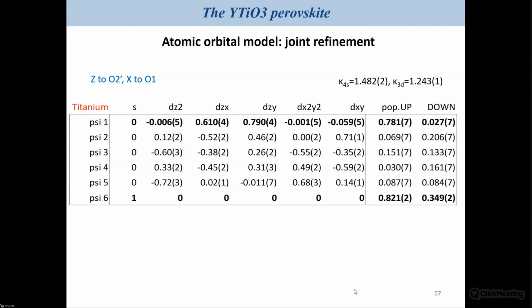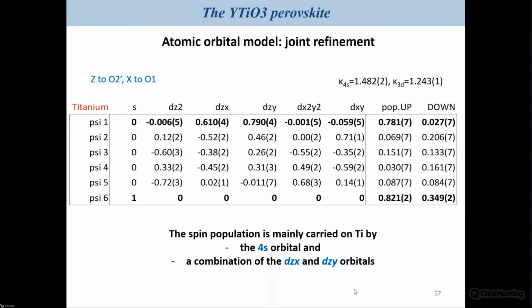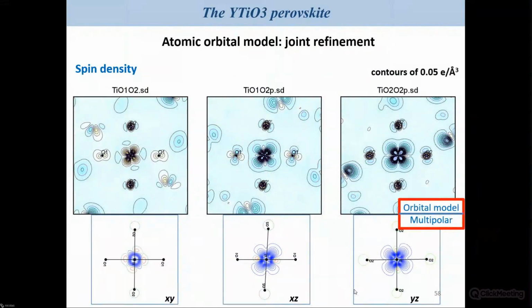I will focus on the titanium atom because it's the one possessing non-paired electrons. And you observe in that case that the spin population is mainly carried on titanium by 2 orbitals. The first one is the pure 4s orbital, and the second one is a combination of the dzx and dzy orbitals. And what is interesting to see is that if you compare the orbital model to the multipolar model, you see that the maps are very close for both models, as you can see here on the maps plotted with contours of 0.05 electron per angstrom cube, because it's something which again shows that the major contribution comes from the dxz and dyz planes.